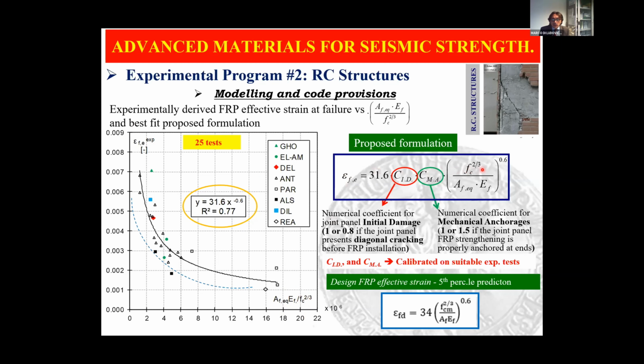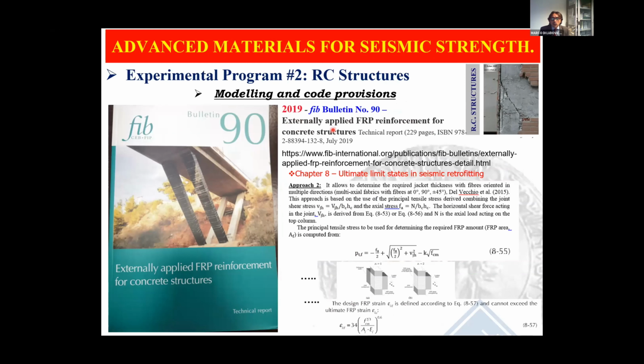And this is the proposed formulation, which has a good match with the experimental results. And it also takes into account the initial damage of the joint or the use of mechanical anchorages. Then, to give practitioners a formulation, we move from here to here, and this is the value that can be used in design applications, so the 5th percentile. And this expression was also inserted in the last FIB bulletin related to the use of externally applied FRP reinforcement for concrete structures.